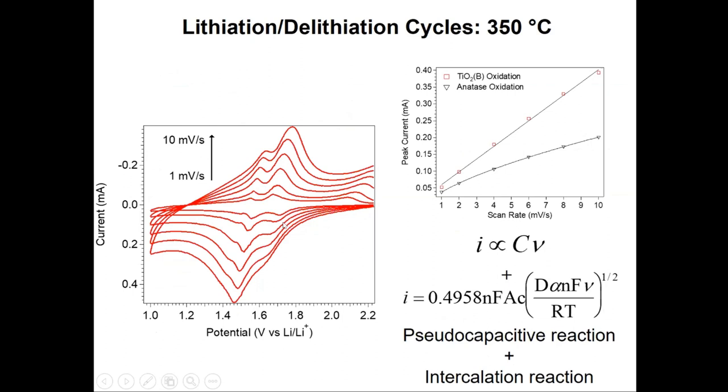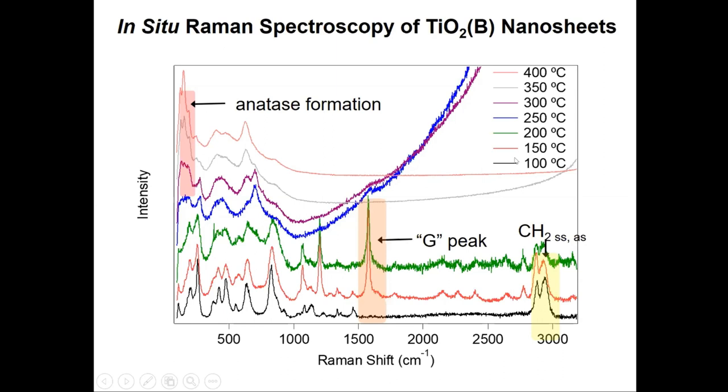And it gets more complicated than this, but what we could show is as we heat this material up, we could follow the degradation of the capping ligand that maintained the stability of the nanosheet. It starts to form graphitic carbon due to the degradation of the ethylene glycol that stabilizes the nanosheet morphology. And then we could actually see, as we heat this up to roughly 400 degrees C, all of the TiO2-B converts to anatase. And that's a nice thing to understand in terms of material processing characteristics, because if you